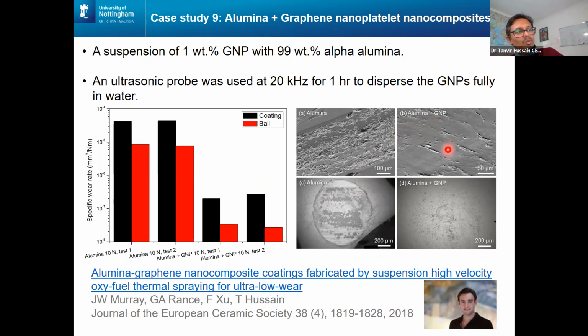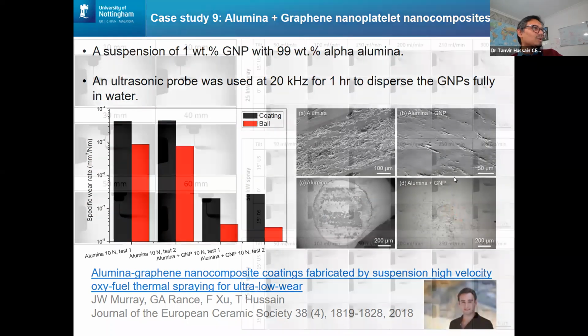And when you have 1 weight% graphene nanoplatelet in the alumina, there is barely a scratch, and the spot on the alumina body is also quite small. In the wear terms, we have specific wear loss in millimeter cube over Newton meter, on a log scale, and it drops by 2 orders of magnitude in that case. So there's a significant improvement in reduction of wear when you add something like 1 weight% graphene nanoplatelet as a reinforcement material. That was James's work at the time.